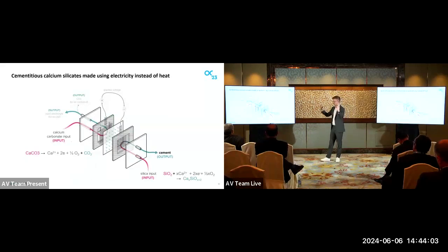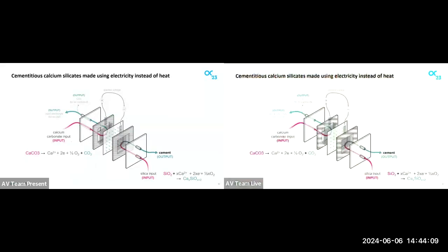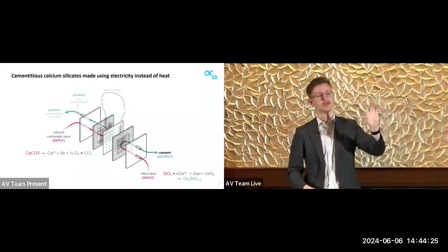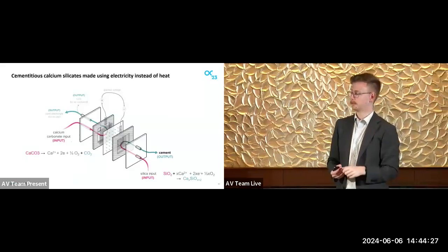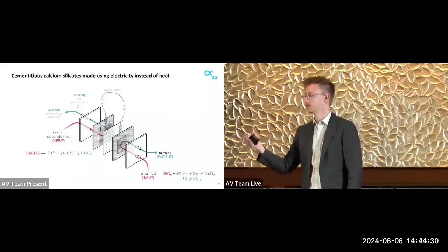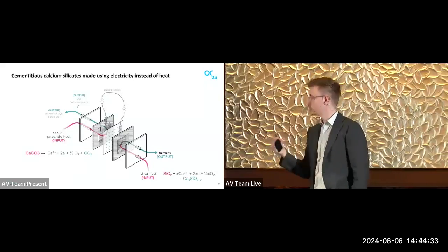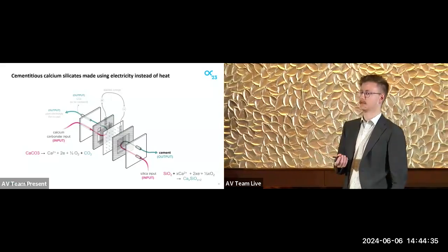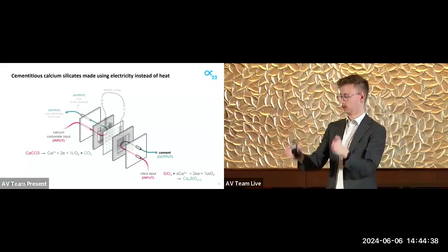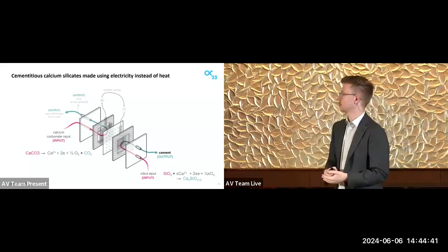And so kind of what is happening under the hood in this large scale is we're doing the same cement production chemistry. Instead of using heat, we're using electricity, a voltage. So just like you would charge a battery to move ions from one side of a cell to another, we're doing that with cement. So, step one, you have a calcination reaction. So we do that with our oxidation part of our cell. And then step two, you have a clinkerization reaction. So we make the clinker of the future. It is still a hydraulically active calcium silicate. We do it all in one single cell, all with less energy input.